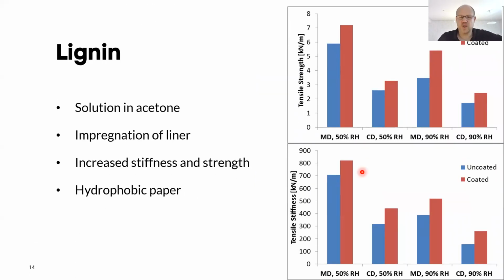We also did pre-trials with it, some years ago, where we dissolved it in acetone and impregnated liner with it, and we could actually improve both the stiffness and strength, especially at high relative humidities. We also had a very hydrophobic paper, so if we could make this work with water, it would be really nice as a replacement for starch. I know that there has been other research done in a similar way with solvents, making lignin barriers. The problem is that you can't really use these kinds of solvents in an industrial environment.